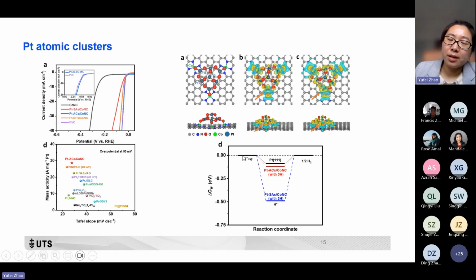And also when we calculate the free energy of this atomic cluster and the single atom for the HER, we found the atomic cluster shows much better performance compared to the single atoms. So that means the platinum-oxygen-platinum unit is a very good place, or active site, for the HER.